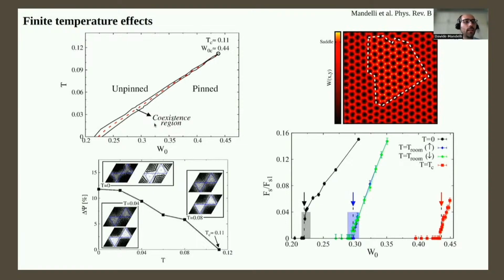Actually, because of finite size effects, the coexistence line becomes a coexistence region, and of course, we observe coexistence of these two phases within the same monolayer in our simulation, as shown here. And along the whole coexistence line, we observe the same kind of Aubry-like signature, with avoidance of the maximum of the substrate potential while going from below to above the critical value of the substrate potential.